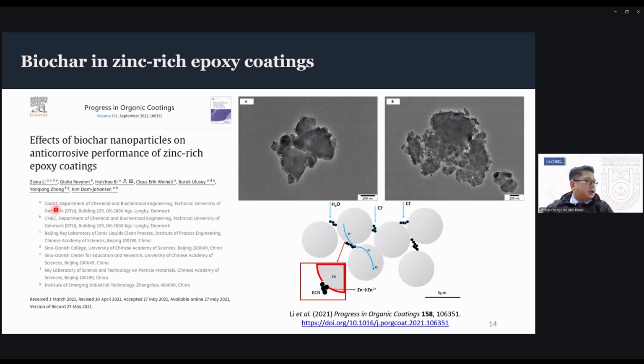This group is a center that specializes in coating studies. What they've done here is start with the hypothesis: you have zinc-rich coatings which already perform quite well, but are there ways you can even improve the utilization of zinc inside these coatings? In the past, before using biochar, people have tried to do it with carbon nanotubes, carbon fiber, graphite, graphene, which I've already talked about, and also reduced graphene oxide.